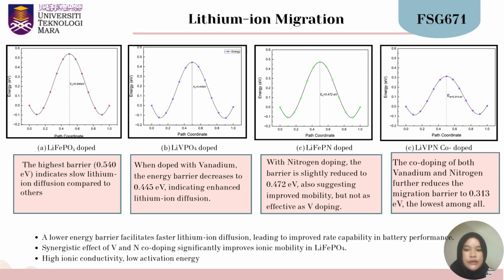In pure LiFePO4, the migration barrier is 0.540 eV, which is quite high. This happens because the path for lithium ions is narrow and there is strong repulsion between lithium ions and oxygen atoms in the crystal structure. When vanadium is added, the barrier drops to 0.445 eV. Vanadium changes the structure a bit, making it easier for lithium ions to move by reducing the repulsion and making the lattice more flexible. With nitrogen doping, the barrier lowers slightly to 0.472 eV. The nitrogen causes some distortion that helps lithium ions move better, but not as much as vanadium.